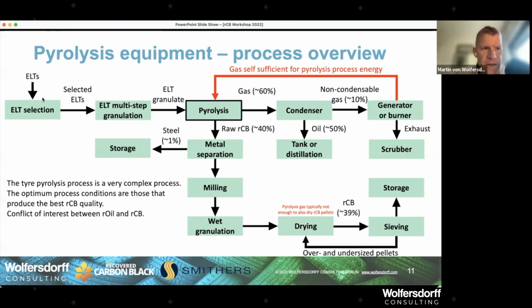The end-of-life tires, we need to select the end-of-life tires. One reason is, as I mentioned, to control the ash content or the inorganic content. Then we go into a multi-step granulation. Sometimes it's only the first shred, but certainly for continuous processes, there's a trend to smaller particles. It used to be 20 millimeters. Now companies are looking at 6 millimeters.